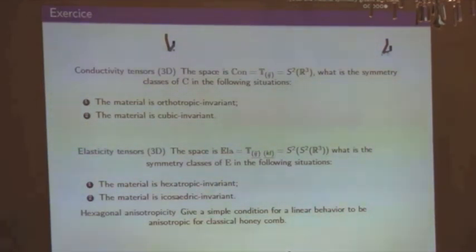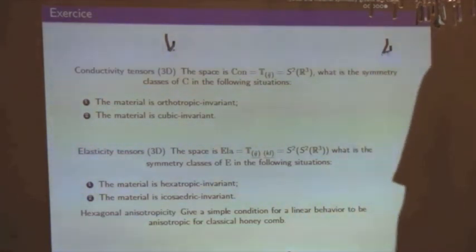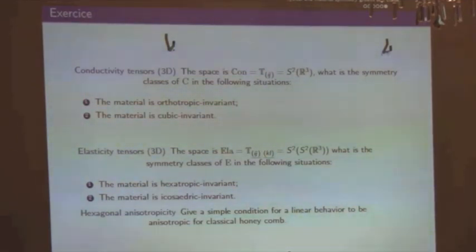Strain gradient elasticity is defined by a 6th order tensor. So for a hexagonal tiling like a honeycomb structure, we know without making any computation that strain gradient elasticity may be anisotropic for hexagonal structure. And in fact, adding some results I don't tell you today, it's not a possibility, it's an obligation to be anisotropic for hexagonal elasticity without making any computation. So I think using groups is sometimes a very beautiful way to get a global structure very quickly.